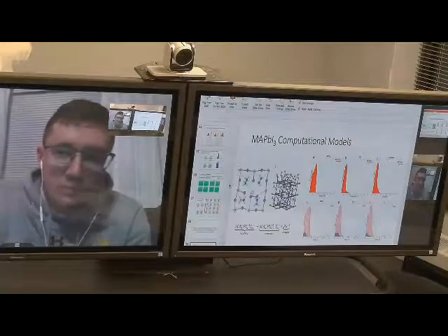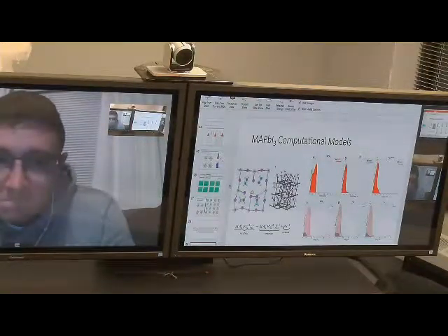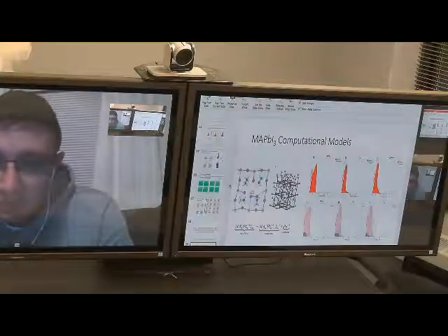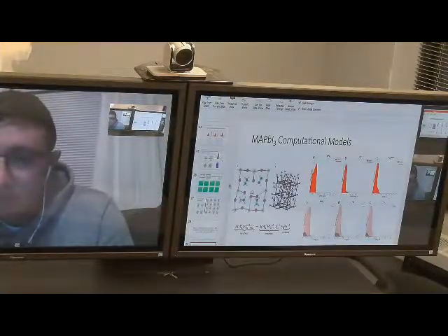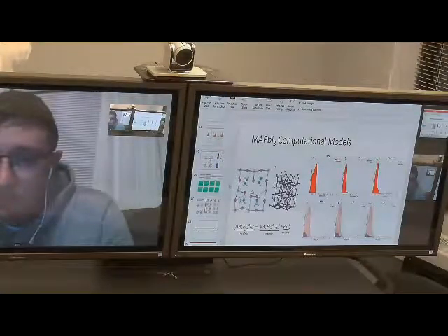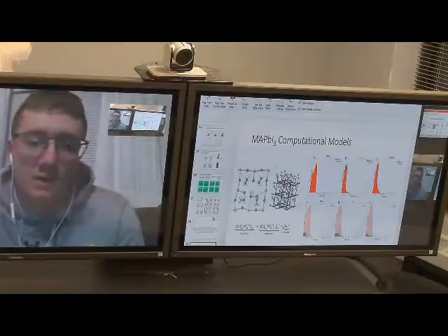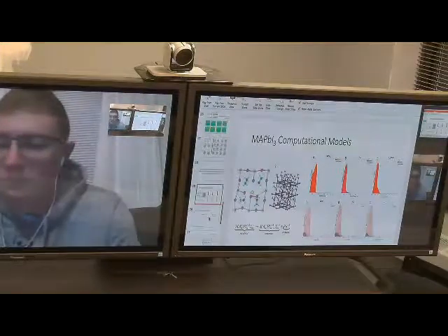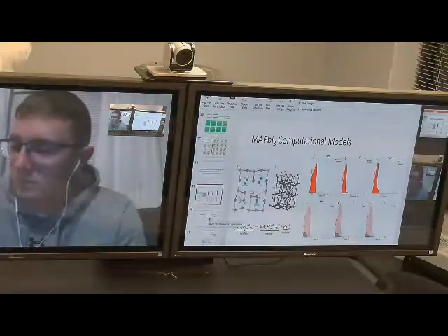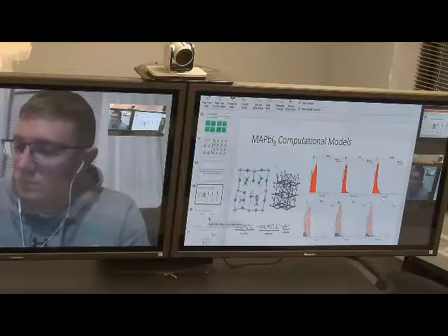May I interrupt you? For curiosity, when you have bulk perovskite, the lead ions contribute orbitals to the bottom of the conduction band. And you can mention them, like 5s. Okay, yeah, I'll put something like this. And here's the question. If you remove one lead ion, you also remove these 5s orbitals from the bottom of the conduction band. Why do you observe formation of a trap state in the middle of the gap?